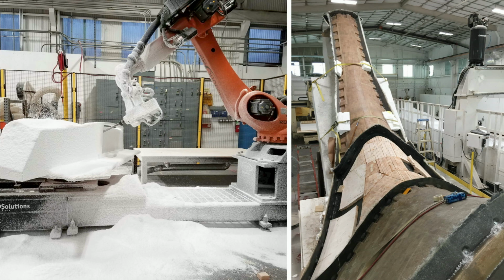One of the biggest advantages of using this method was that the milled surface of the foam positive was highly accurate, and that all accumulation errors inherent in the fabrication were offset from the surface instead of working towards it. If we had used a traditional plywood formwork system, the CNC milled ribs would have been produced first, and then layers of plywood would be layered up from there, accumulating error each time, so the largest error was closest to the final surface.